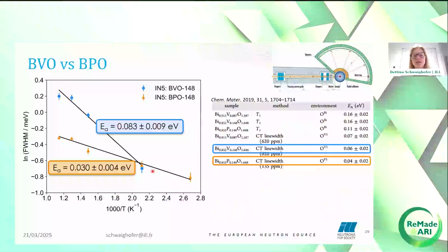From this, we could obtain the activation energy of the picosecond dynamics. For BVO, we found this to be 0.08 electron volts, and for BPO, 0.03 electron volts. Again, this is in great agreement with NMR data and suggests that on IN5, we observe dynamics in the dopant sublattice.